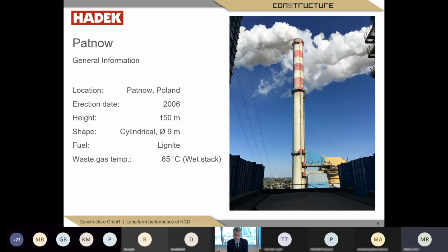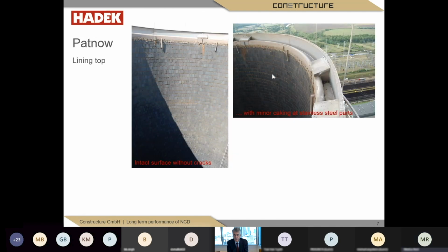The fuel of the power plant is lignite, and as you can see in the picture on the right hand, it is a wet stack with water-saturated flue gases and a flue gas temperature of about 65 degrees centigrade. And here you can see the first pictures after more than 10 years of operation from the very top. We did a lot of photographs. Here is a short selection.